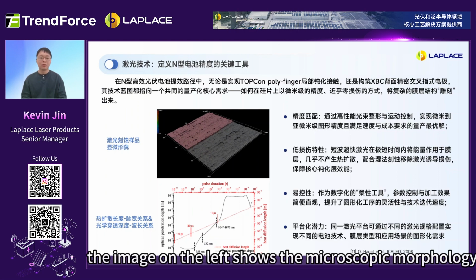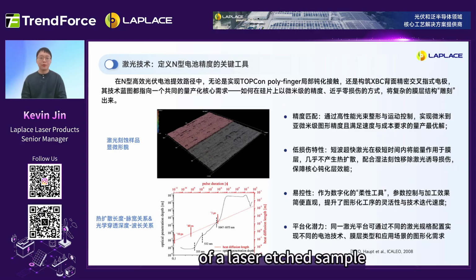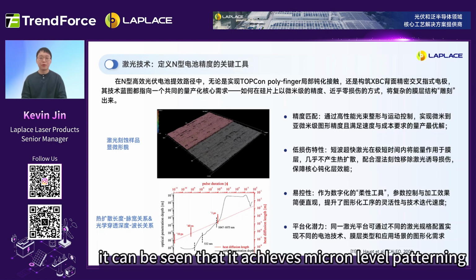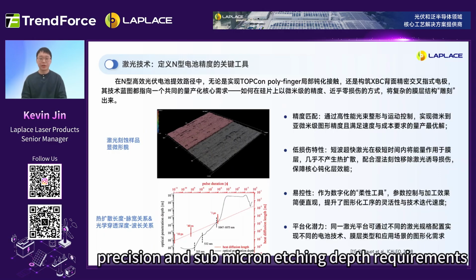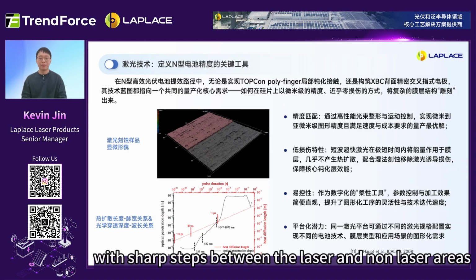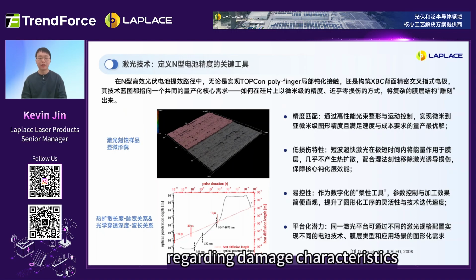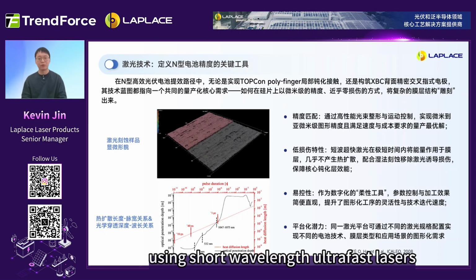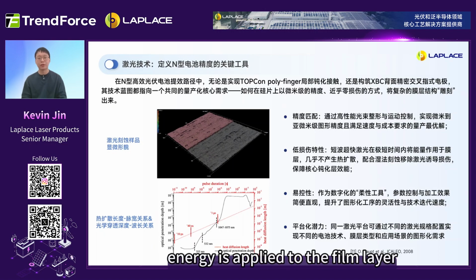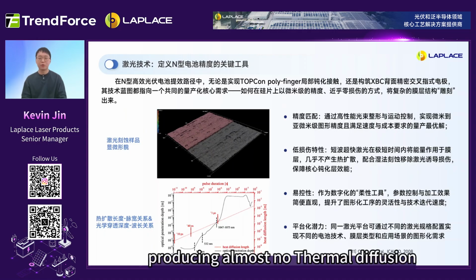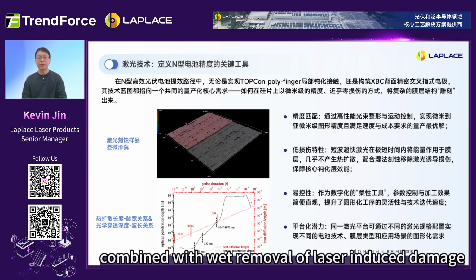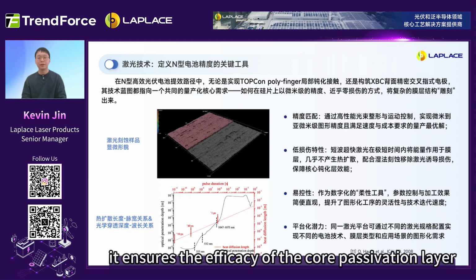The image on the left shows the microscopic morphology of a laser-etched sample. It can be seen that it achieves micron-level patterning, precision, and sub-micron etching depth requirements, with sharp steps between the laser and non-laser areas. Regarding damage characteristics, using short wavelength ultra-fast lasers, energy is applied to the film layer in an extremely short time, producing almost no thermal diffusion. Combined with wet removal of laser-induced damage, it ensures the efficacy of the core passivation layer.